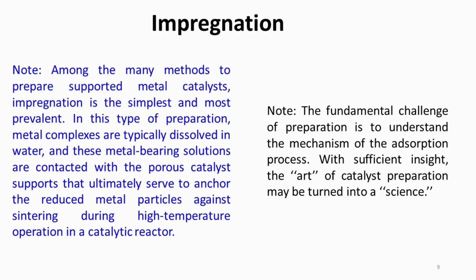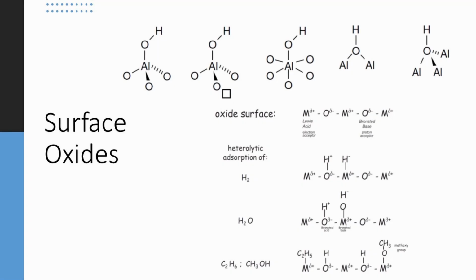Metal oxide surfaces are commonly terminated by hydroxyl groups. Depending on the metal oxide lattice structure and the detailed bonding, the OH groups are acidic, neutral, or basic. Using infrared spectroscopy, it can be confirmed that OH groups are present at the surface of, for example, gamma alumina, which can be considered basic if the OH group is bonded to one aluminum, neutral if bonded to two aluminums, or acidic if it is a bridged OH bonded to three aluminums. Similar statements can be made for other oxide surfaces.